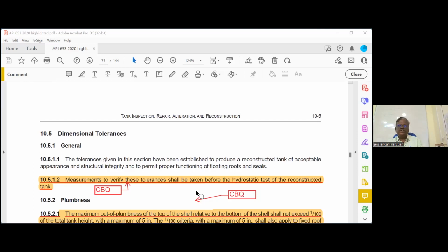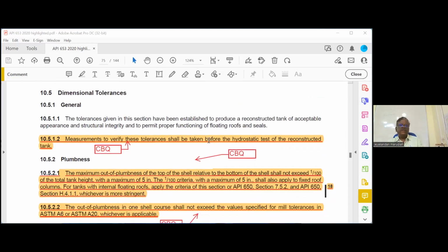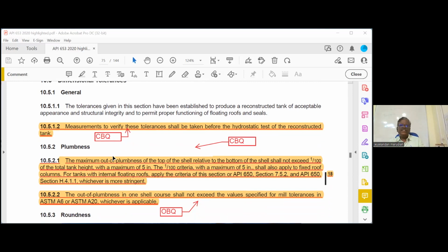Then next, dimension tolerances. Measurements to verify this tolerance shall be taken before the hydrostatic test of the reconstruction. When you have to take this plumbness, everything is before the hydrostatic test. That is important. Close book question. Now, here there is a change. For construction as per 650, what is the out of plumbness allowed? 1 by 200. Here it is 1 by 100, but there is a maximum limit. Maximum only 5 inch allowed. There is no maximum limit in the 650.